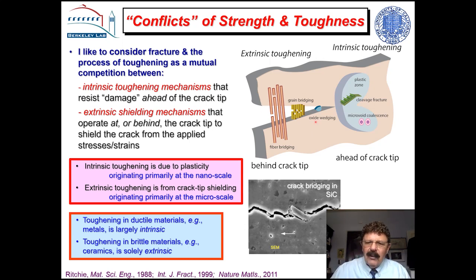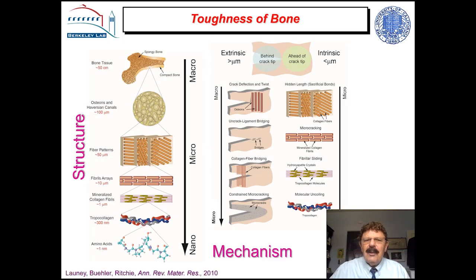But biological materials seem to be able to combine both these mechanisms quite readily, and they do that by having multiple length scales in their microstructures. This is bone. It has characteristic dimensions at the nanoscale, twisted peptide chains, mineralized collagen fibrils, all the way up to the osteonal structure and the bone itself. So if you look at the mechanisms of toughening in bone, they combine both intrinsic and extrinsic.